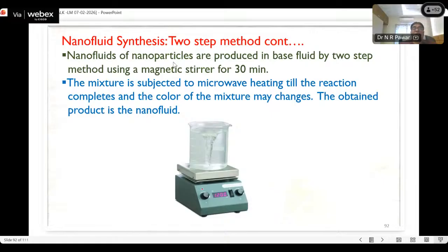The mixture is subjected to microwave heating till the reaction is completed and the color of the mixture may change. The obtained product is the nanofluid. Thus we have synthesized the nanofluid by using this two-step method that we have discussed. In the first step, we synthesize the nanomaterial. That nanomaterial is dispersed in the base fluid, and mostly for the synthesis of the hybrid nanofluid, we use ethylene glycol. After that, by using a magnetic stirrer or ultrasonication, we obtain the hybrid nanofluid.